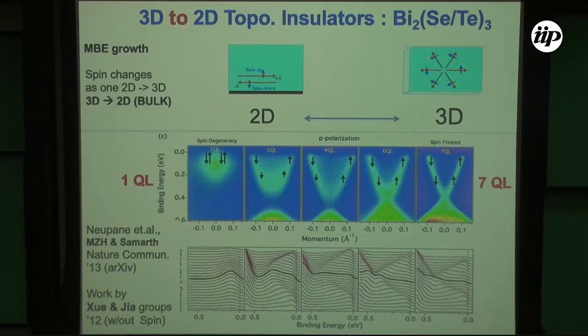That we can also experimentally vary. If the bismuth selenide film is 7 nanometer, or what we call 7 quintuple layer, spectroscopically we can clearly see a Dirac cone and its spin texture. Now if you make a thinner film, 6 nanometer, 4 nanometer, 3, then you can see that this is broadening up. At some point, there's a gap opening. Now the top and bottom surfaces talk to each other. They're not isolated or independent.